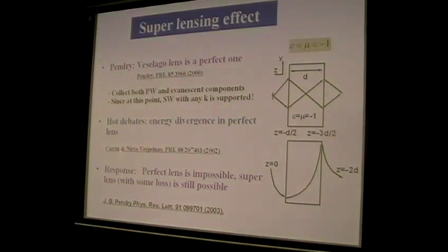On this famous paper, there was a very hot debate. A Spanish group pointed out that it is actually not correct, because if you do that, you will find the energy will diverge at this exact interface. The reply of Pendry is that the perfect lens is indeed impossible. However, a super lens, if you add some loss into this material, is still possible. Super means that we can still beat the common diffraction limit, the λ/2 diffraction limit.